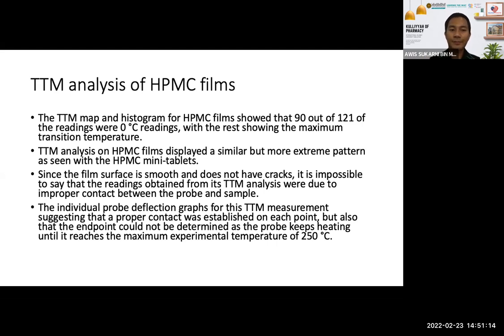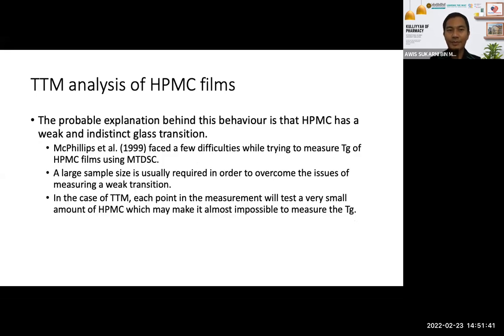And since the surface of this film is basically smooth, so there is no crack, it is impossible for us to say that the reading obtained from this TTM is because of improper contact between the probe and the sample. So what they did is, when they couldn't determine the actual transition temperature of that area, they record it as either 250 degrees or 0 degrees.